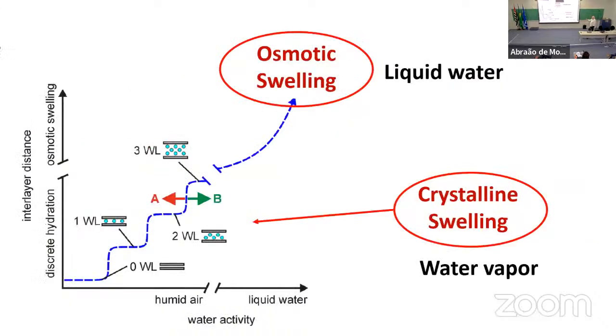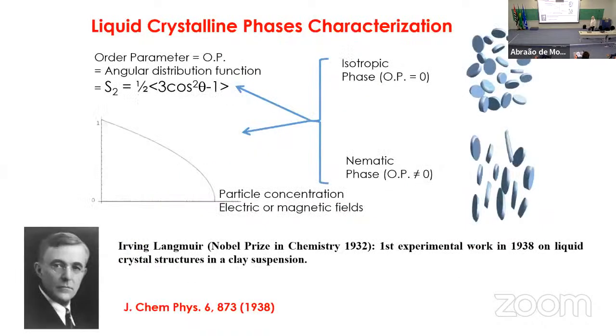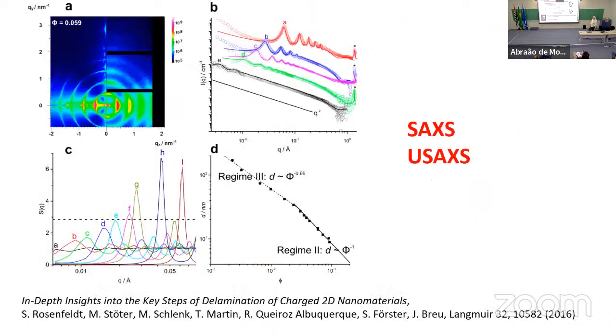So now I talked about the crystalline swelling, and now osmotic swelling in liquid water. That was actually studied. The first paper we in this area are aware of was by Langmuir, 1930. Well, he got the Nobel Prize in 32, but his paper on clays was in 1938, and he suggested that when you exfoliate these clays in water, they form nematic phases, meaning that the 1 nanometer thick platelets are separate in water. And if the concentration is high enough, they are not able to rotate. So then you get a nematic organization in the suspension.